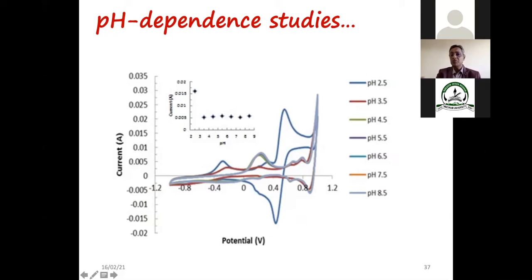So most of the studies people are doing are at very low pH values. At low pH, the peak current, the signal that we will be getting, is very high. Here, arsenic 3 was measured at low pH, and the very high signal that we get is shown in this figure.